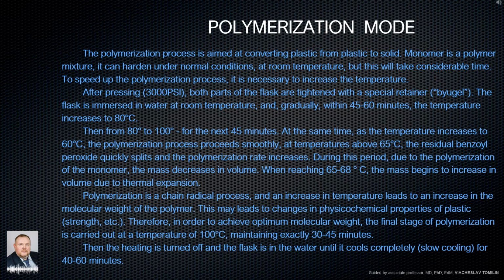After pressing, 3000 psi, both parts of the flask are tightened with a special retainer. The flask is immersed in water at room temperature, and, gradually, within 45 to 60 minutes, the temperature increases to 80 degrees Celsius. Then, from 80 degrees to 100 degrees, for the next 45 minutes. At the same time, as the temperature increases to 60 degrees Celsius, the polymerization process proceeds smoothly. At temperatures above 65 degrees Celsius, the residual benzoyl peroxide quickly splits and the polymerization rate increases. During this period, due to the polymerization of the monomer, the mass decreases in volume. When reaching 65 to 68 degrees Celsius, the mass begins to increase in volume due to thermal expansion.